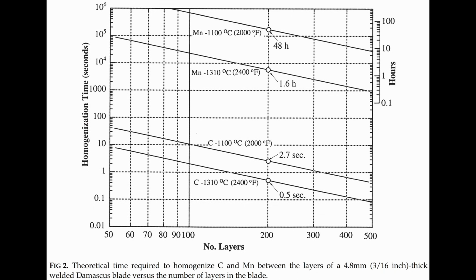Now, other elements take longer to equalize. So at the same 2,000 degrees, looking at manganese instead, it takes over 48 hours for the manganese to equalize in the steel at 200 layers. Carbon is a much smaller element, and so it diffuses relatively quickly.